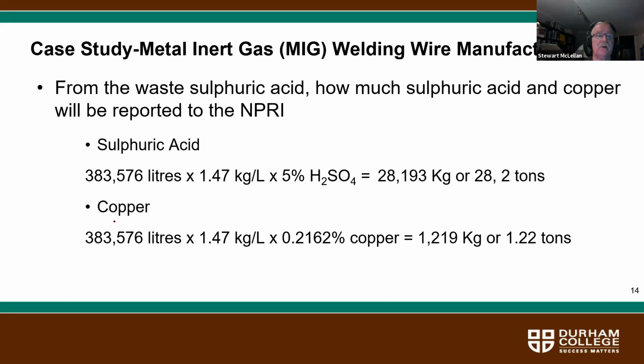When we come to copper, it's essentially the same calculation, except instead of 5%, we multiply by 0.2162% for copper, and we end up with 1,219 kilograms or 1.22 tons of copper in the waste stream. So you can see from these calculations that you need to be reporting to the National Pollutant Release Inventory that you released or disposed of 28.2 tons of sulfuric acid and 1.22 tons of copper.